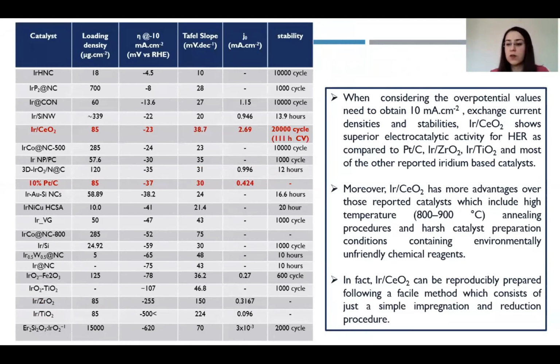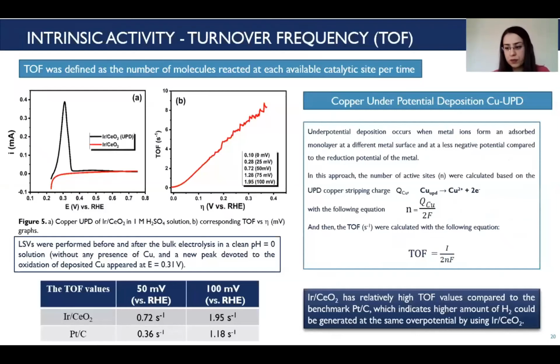In fact, iridium ceria can be reproducibly prepared following a facile method which consists of just a simple impregnation and reduction procedure. Also, intrinsic activity was observed by calculating the turnover frequency values. To calculate the turnover frequency values, the copper underpotential deposition method was used, and in this approach, the number of active sites was calculated based on the copper stripping charge.